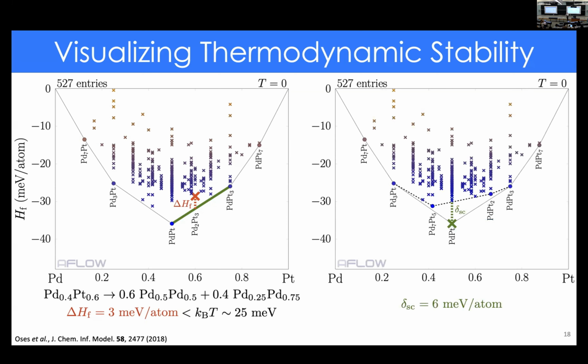We took this concept and flipped it on its head, because there are often times when we do materials discovery where we get a lot of stable structures. Now we need to sort through and figure out which are the most stable structures that are most likely to form. So how do we differentiate between those that are predicted to be stable? We defined a criterion very similar to the decomposition energy. If we're interested in understanding how stable this point on the hull is, we take this point, remove it, and recalculate the hull without it. You see how the shape changes. Then we calculate the y distance between the point and the new hull.